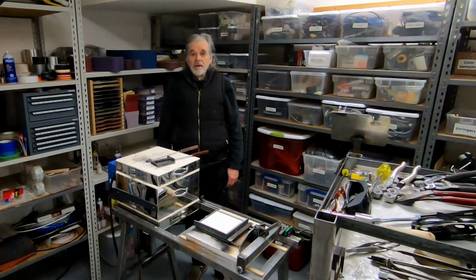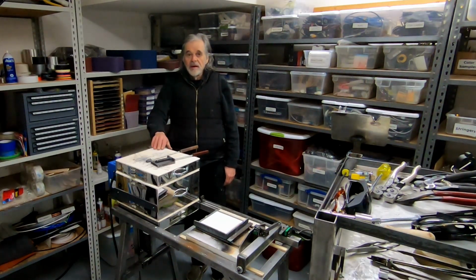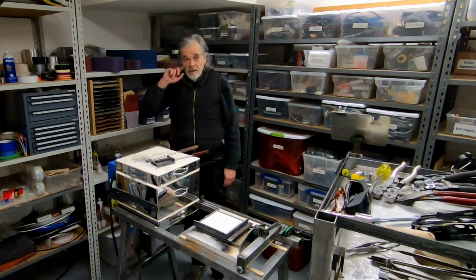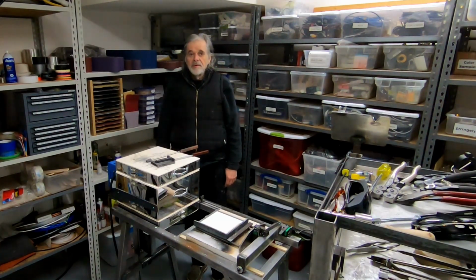It didn't produce the same scale, but had the same red hot sticking problem, and over time it tended to warp. Then I switched to a graphite plate in my old process before I got the higher temperature kiln, and the graphite plate worked, but graphite is an organic material, and it burns in an oxygen atmosphere. In an inert atmosphere, it'll take up to 3,000 degrees, but in an oxygen atmosphere, graphite burns.